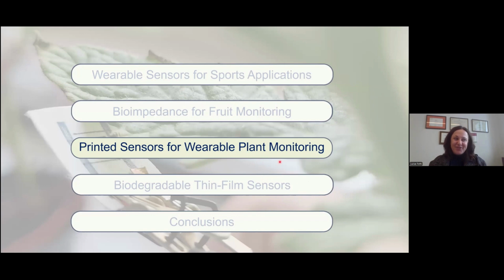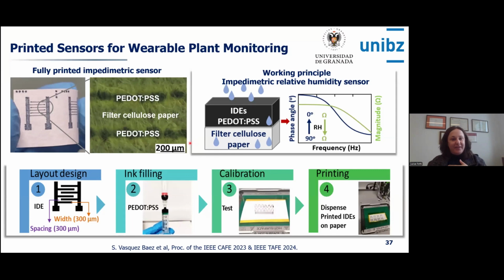Good. I want to show you also a little bit of the work on plant monitoring, in particular using very simple sensors. So those are impedimetric, so again, impedance, printed sensors on cellulose, on a filtered cellulose paper using PEDOT:PSS interdigitated contacts that are completely printed in this way with a different printing technique. We're talking about dispense printing. That is a digital printing technique, and we're looking at the variation of the impedance with the relative humidity. So the concept and the sensor are extremely easy.